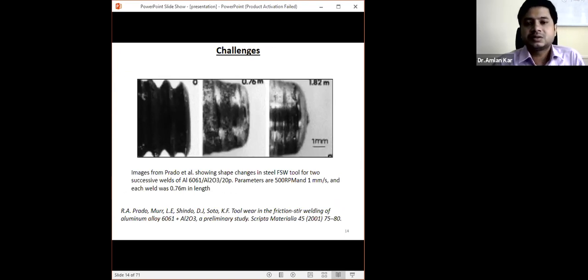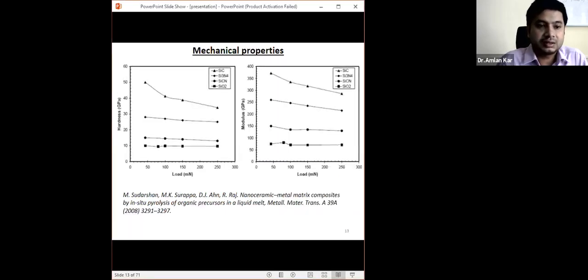The major challenge is that because of the higher hardness of the ceramic particles, you know, the hardness I have discussed here, the hardness is very high compared. You can see it is in gigapascal. So since the hardness is very high, it actually creates wear on the surface of the tool. Okay, so our tool is rotating continuously. So when this tool material comes in contact with ceramic particles, the ceramic particle creates a crater on the surface, and therefore the surface of the tool is subjected to wear and tear.